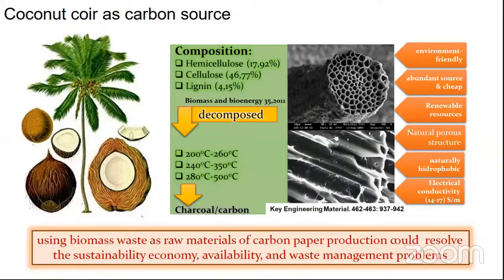We can see the original coconut coir structure, namely fiber, with several parallel hollow tubes close to each other. Using greater magnification, we also observe pores with a diameter around 1 micrometer spread in the fiber cell wall. Owing to its chemical composition and unique morphology, coconut coir waste can be recycled or utilized as a renewable and relatively inexpensive carbon precursor, even a graphite precursor, with additional treatment.